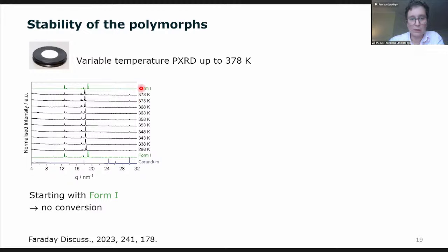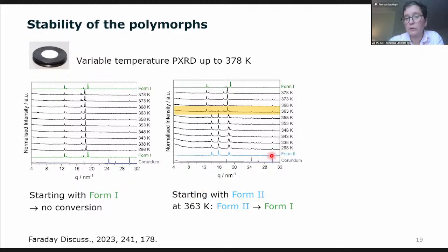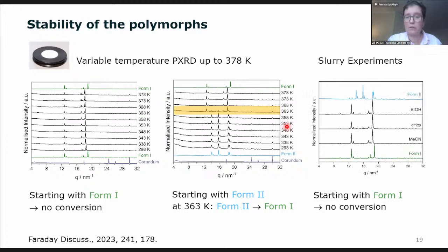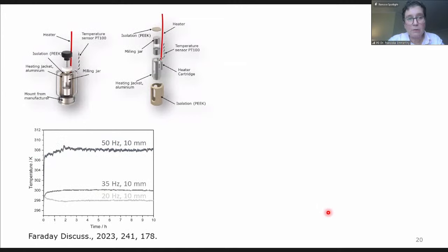But if we start with form two and heat it up, you can see that here at 363 K, we have the conversion to form one. We then also performed slurry experiments to see which one is the thermodynamically stable product. And you can see here that's also form one. When we start with form one, we have no conversion. So this is the stable form here. Then we did our temperature measurements. You see here the milling vessel we used before, but now it's in a little jacket, a heating jacket, where we can apply temperature and keep the temperature at a certain level.